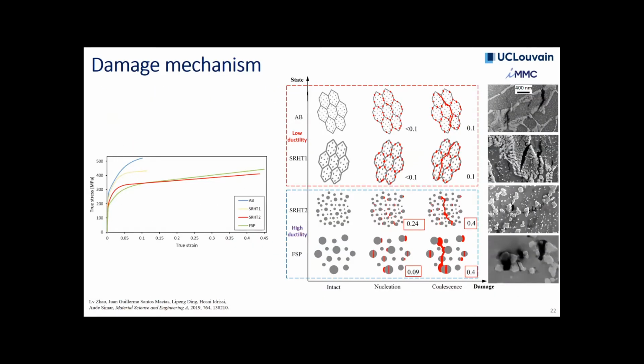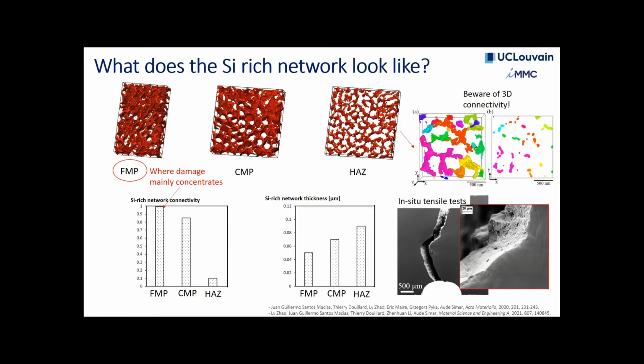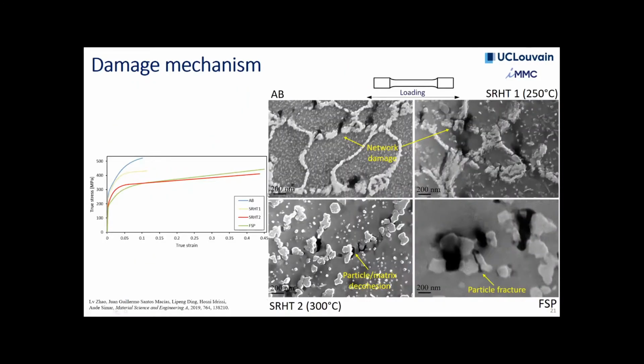Yes, I probably should have mentioned that. It's a bit more complicated than that, because I think at certain porosity levels, what you're mentioning is the fact that these have very different porosity and still have the same ductility. Our feeling is that damage is mainly nucleating on these networks. So mainly it's the silicon network that causes the damage, and we're looking at in situ tests performed in the synchrotron and doing some tracking of these porosities and seeing how they influence the coalescence. So I'll have some more detailed answers in the future.